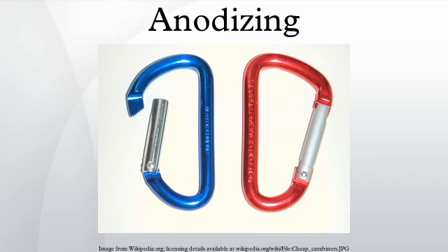Borate and tartrate baths. Anodizing can also be performed in borate or tartrate baths in which aluminium oxide is insoluble. In these processes, the coating growth stops when the part is fully covered, and the thickness is linearly related to the voltage applied. These coatings are free of pores, relative to the sulfuric and chromic acid processes. This type of coating is widely used to make electrolytic capacitors, because the thin aluminium films would risk being pierced by acidic processes.